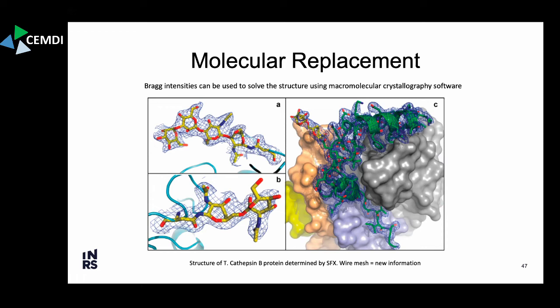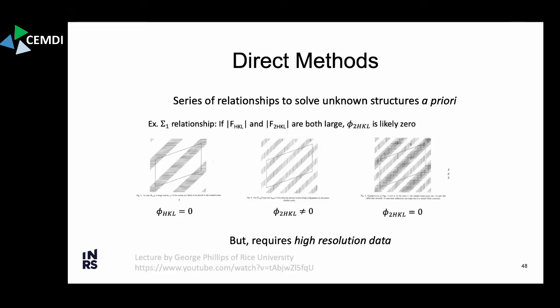But the problem with this approach is the inherent bias. You're highly biased by your starting assumption in the initial structure. In inorganic materials, the approach generally is to use direct methods. And this has its own limitations. This doesn't have any inherent assumptions in the phases, so you can solve structures a priori in this method. But it requires high resolution data to be able to use this.